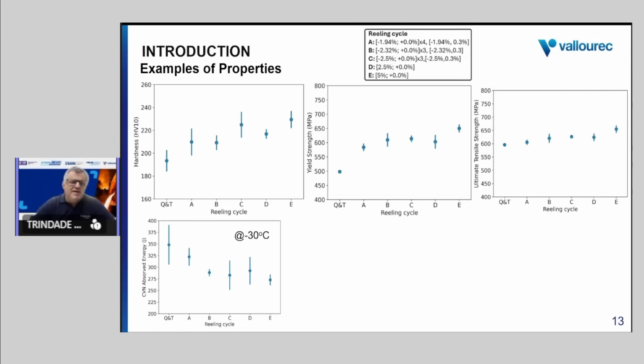Here, just to give you an idea that the material properties are really affected by the reeling process. You can see in this diagram the effect on the hardness. Here is the Vickers, HV10. Here is, I would say, the as-received, heat-treated, quench and temper material at this hardness level. A, B, C, D, E represent different reeling cycles, a combination of compression and tension. From A to E, we increase the final plastic deformation. We can clearly see that the hardness is affected considerably as we increase the final plastic deformation.